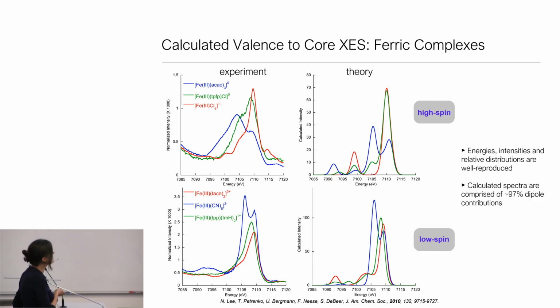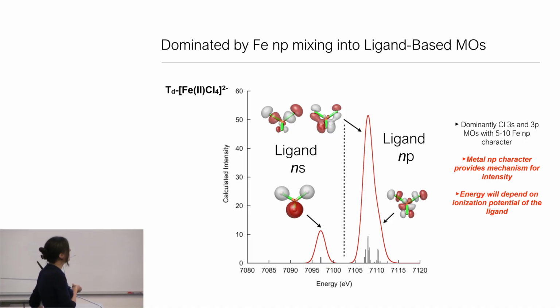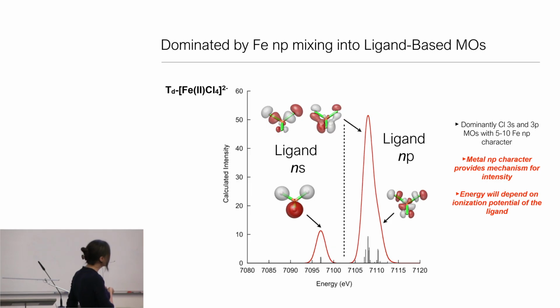And the reason that it works well is largely that these aren't spectra dominated by any complex multiplet effects or anything particularly sophisticated. They largely are transitions that derive from a small amount of metal p character that is mixed into the ligand p and ligand s orbitals. So this is just the visualization of what gives rise to these spectral features based on a simple 1 electron DFT calculation. Now, why do I actually care about this? Well, it gives me a great way to assign what the ligand is.